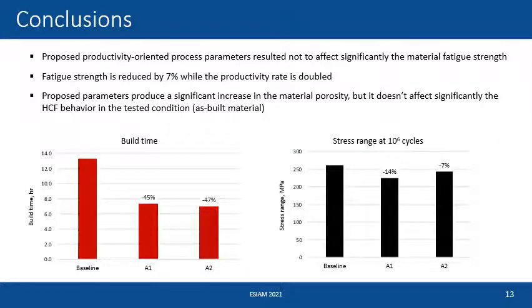To conclude, we can see that the proposed productivity-oriented process parameters do not affect significantly the material fatigue strength, which, if we consider the strength at 1 million cycles, was reduced by only 7%, while the productivity rate is almost doubled. This is the case of the A2 process parameter set.